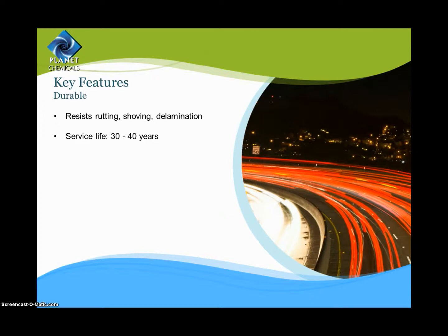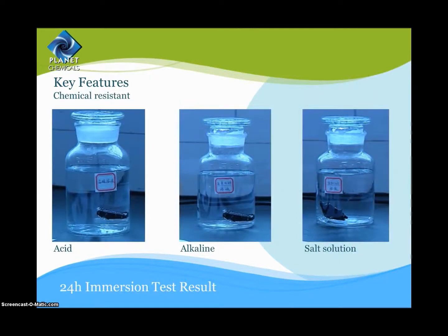Epoxy asphalt resists common failures such as rutting, shoving, and delamination, and has a maintenance-free service life of 30 up to even 40 years. That is more than double that of regular asphalt pavements. Another key feature that places epoxy asphalt as one of the top binder options for durable pavements is its resistance to chemicals.